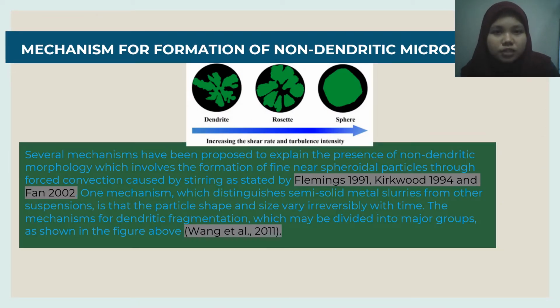Mechanism for formation of non-dendritic microstructure. Several mechanisms have been proposed to explain the presence of non-dendritic morphology, which involve the formation of fine near-spheroidal particles through forced convection caused by stirring, as stated by Flemings 1991, Kirkwood 1994, and Fan 2002. One mechanism which distinguishes semi-solid metal slurries from other suspensions is that the particle shape and size vary irreversibly with time. The mechanism for dendritic fragmentation, which may be divided into major groups, is shown in the figure above, extracted by Wang et al. 2011.